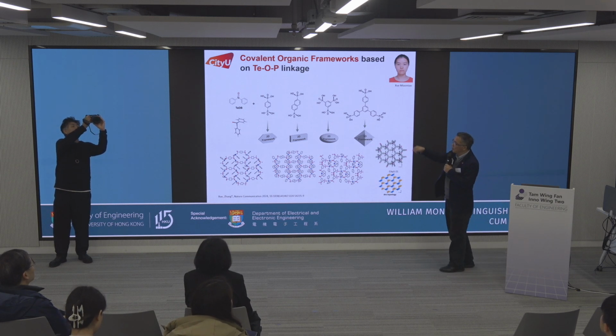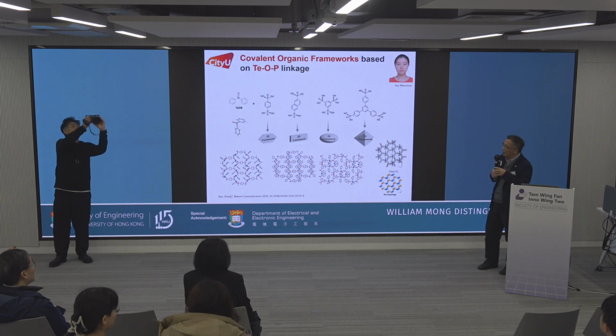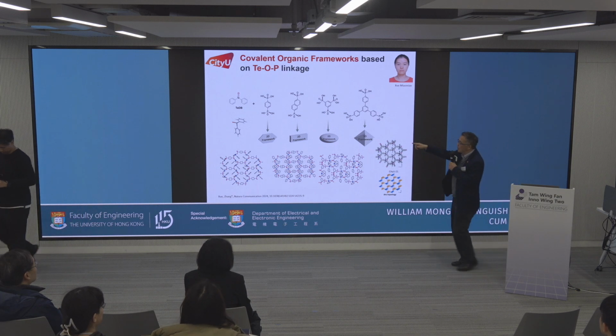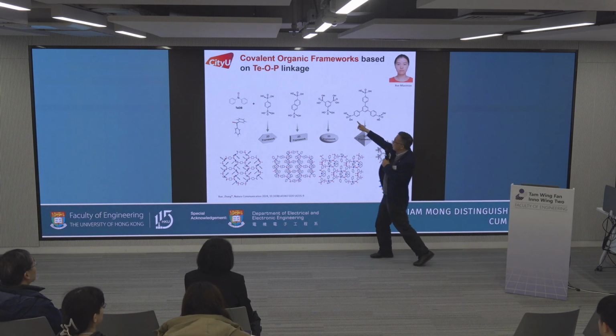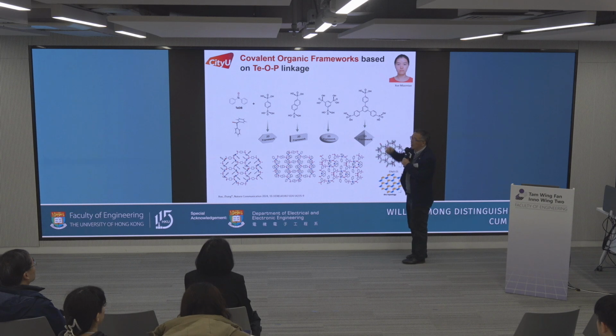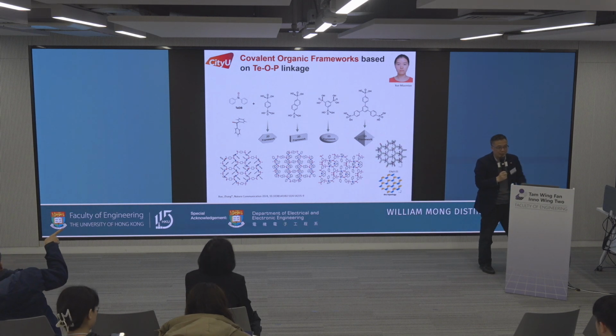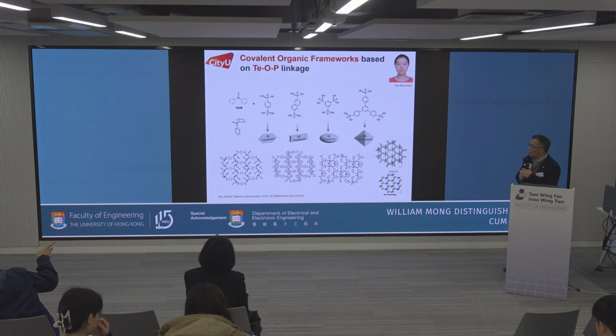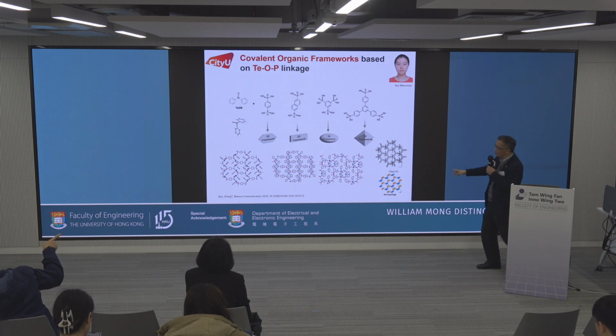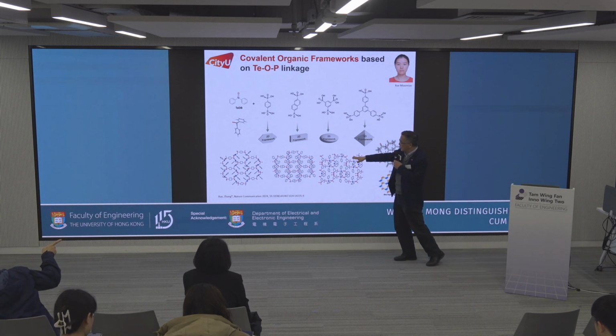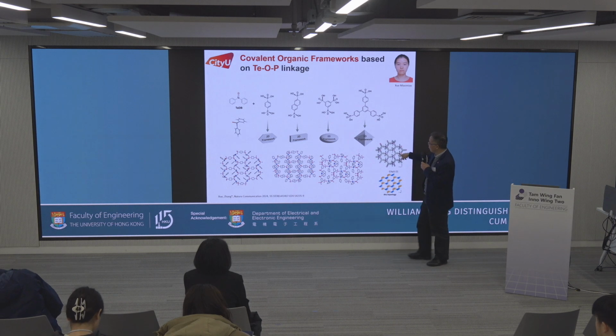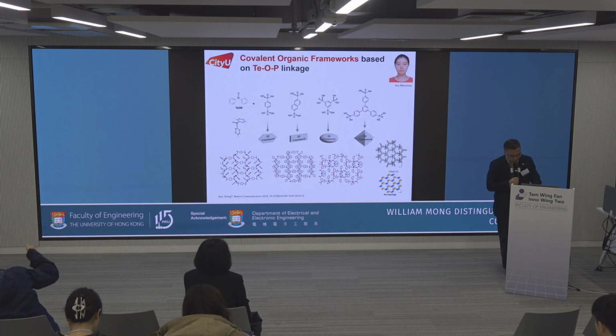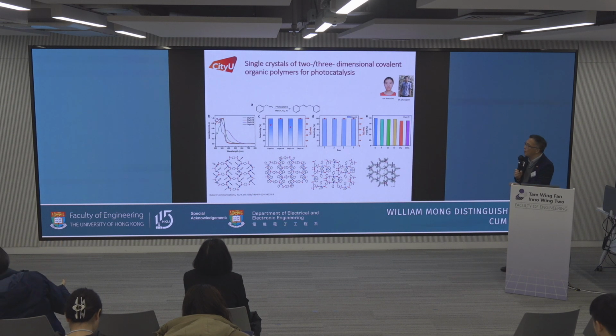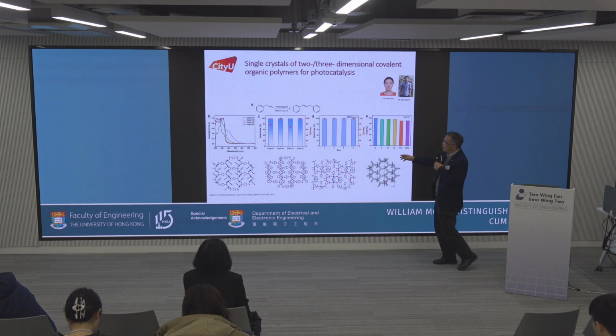For example, we have commercially available 1,4-diphosphonic acid benzene, and then, for example, the benzene can be replaced by naphthalene. Right? We can use the 1,3,5, or we can use the extended phosphonic acid. Okay. So now we can make very nice crystals as shown here. For the first two, we can make 2-dimensional structures, and for the third one, we can make a 3-dimensional framework. As we know, tellurium is a very good catalytic center, so we can use our material to do this reaction.